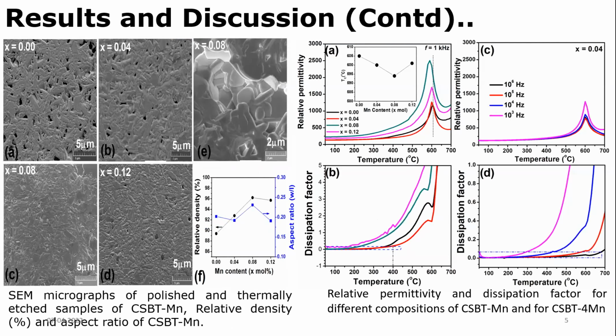Now further to the SEM analysis, here we can see the SEM micrographs of polished and thermally etched samples of CSBT-MN. In the E figure, you can see this is basically of the fractured surface. Here you can see we have observed plate-like features, which is basically due to higher growth in the C axis compared to the A or B axis, which is a nice feature of BLSF. Here in the graph we can see the relative density and aspect ratio versus Mn content.